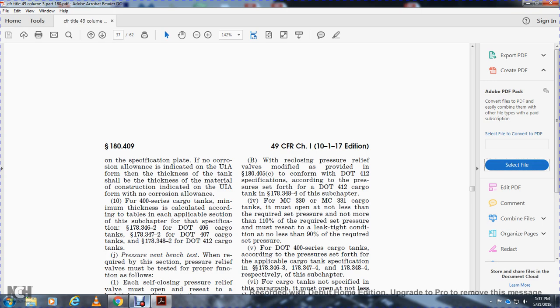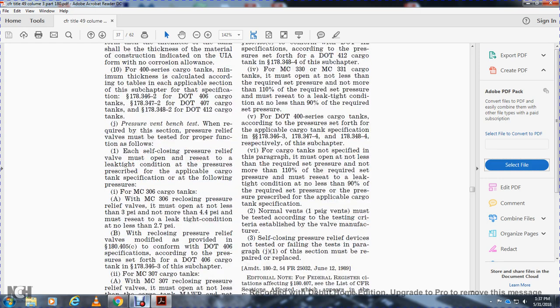Pressure relief valve testing: each required pressure relief valve must be tested for proper function as follows. Each self-closing pressure relief valve must be reset and tested for leak-tight condition at the pressure prescribed by the applicable cargo tank specification. For the MC 306 cargo tank, the reclosing pressure relief valve must open at not less than 3 psi and not more than 4.4 psi, and must retain a leak-tight condition at not less than 2.7 psi.